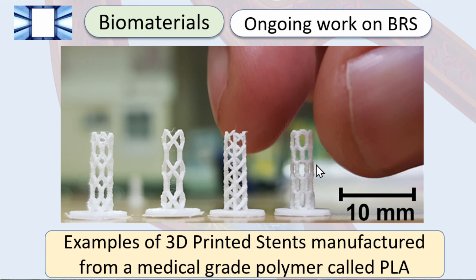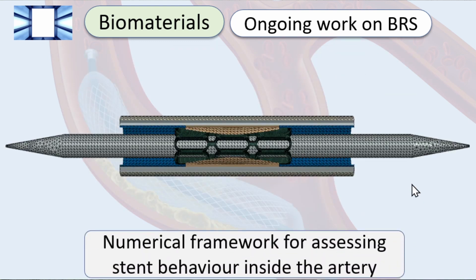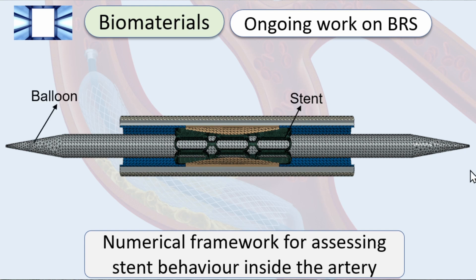We went on to manufacture these stents — these are examples of 3D-printed stents made from a medical-grade polymer called PLA. We then deployed the stents within a finite element modeling scheme. In this model, you have the stent at the center, the balloon that opens up the stent when inserted into the body, the coronary artery, and the plaque. This is the numerical framework for assessing stent behavior inside the artery.